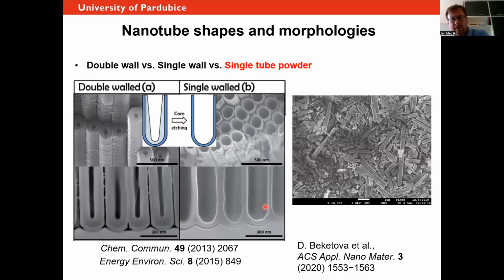as before. And we have actually taken this approach and moved it even farther, and we have over-etched these materials, and we were able to disconnect completely the tubes from the substrate, but also disconnect them from each other. So we were able to do, for the first time, actually powders, nanotubular powders.